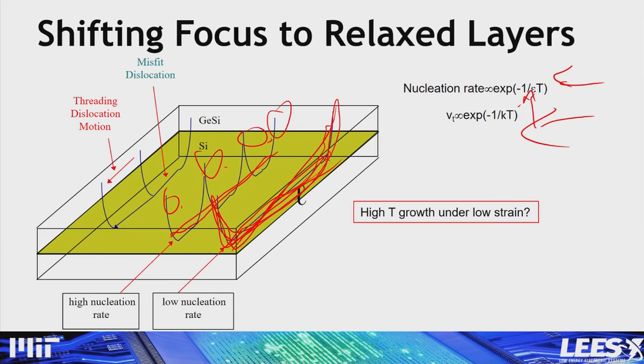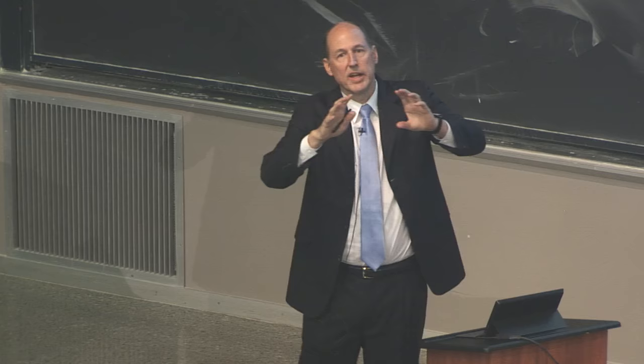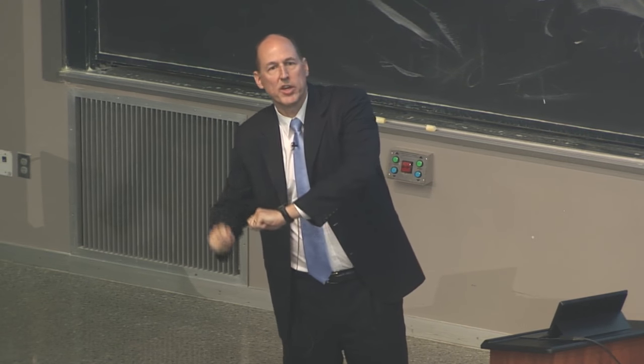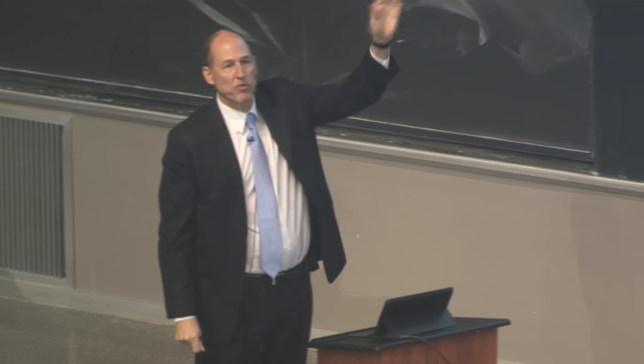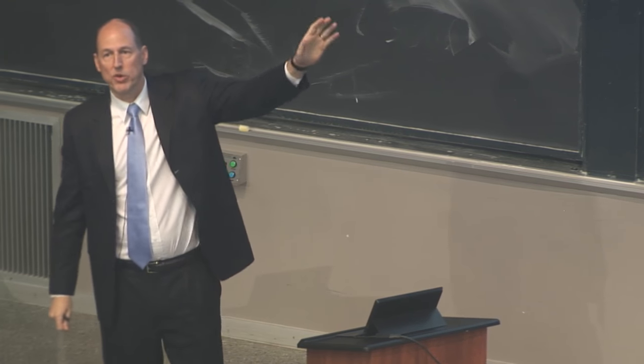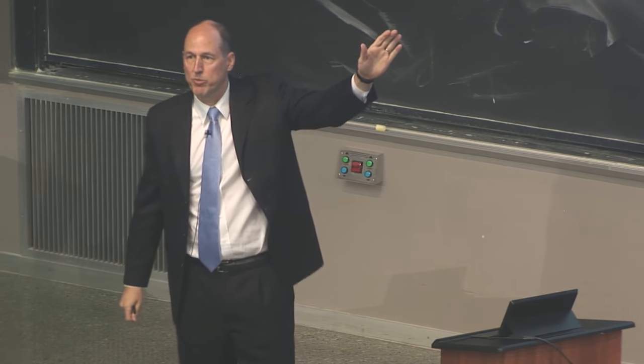If I keep the stress low, which means I increment the mismatch a little bit at a time, but I go to very high temperatures, then you think you could create dislocations where once one enters, it flies across the entire sample, relaxing all that area and preventing other nucleation near it. This was actually counterintuitive because at the time, everybody was going to lower and lower temperatures. They were developing new epitaxy equipment to try to create more and more strained materials. Here we are trying to create relaxed materials, and now we have this crazy idea. We want to go back to older equipment and deposit stuff at really high temperature.